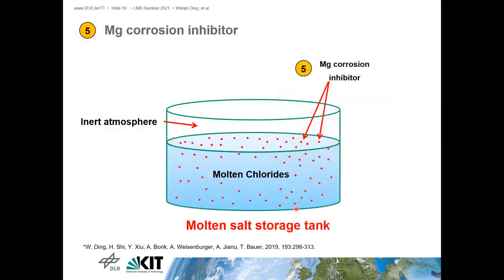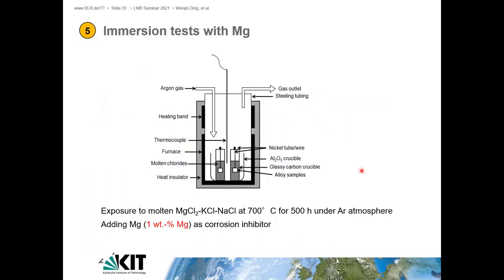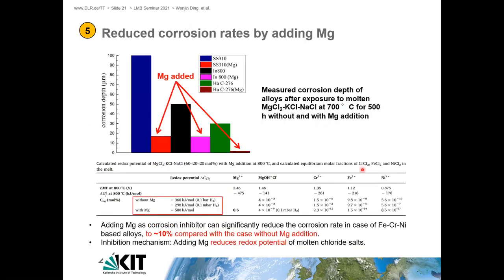So regarding this corrosion mechanism, we have developed a corrosion mitigation method, for example, by adding magnesium as a corrosion inhibitor. We also did a similar corrosion test, but in the molten salt we put some magnesium metal inside. After comparison, with or without the magnesium, we found that with magnesium, the corrosion rate of the conventional alloys is significantly reduced to about 10% compared to the case without magnesium addition.